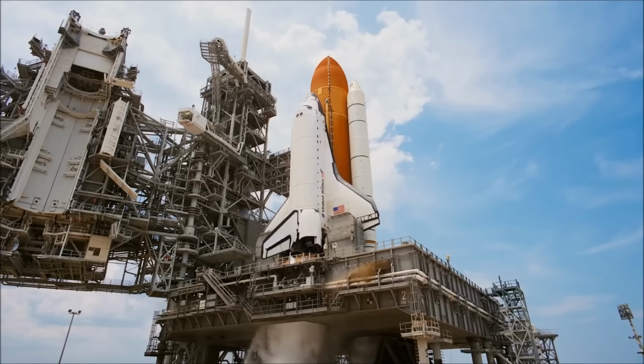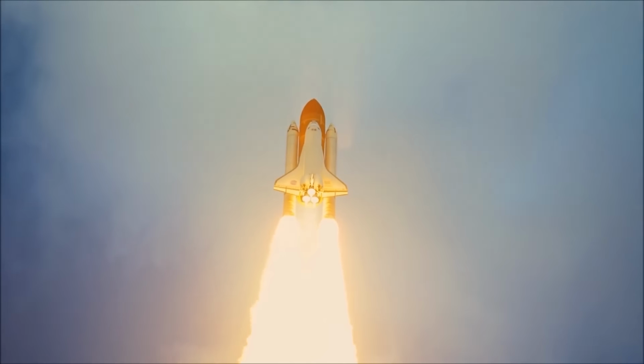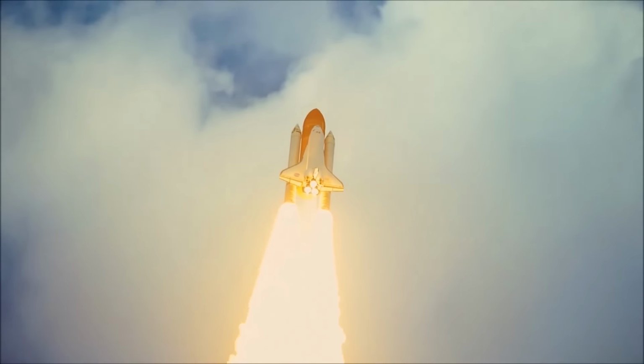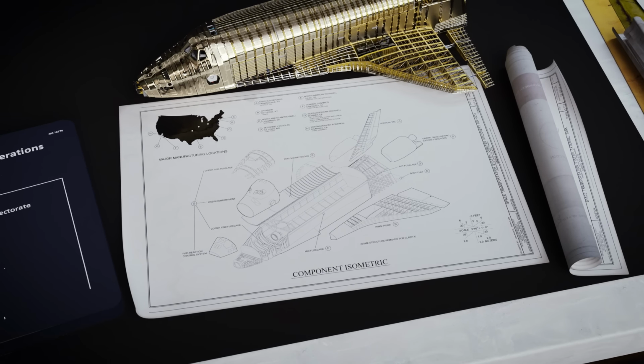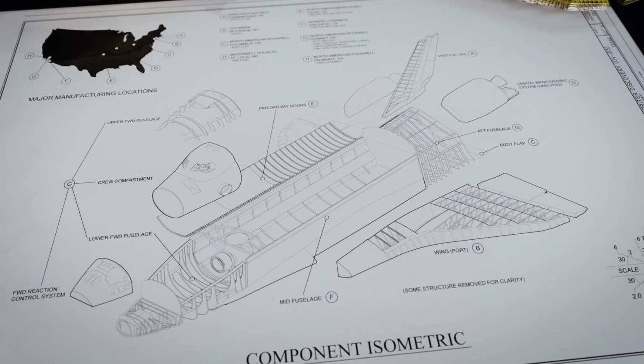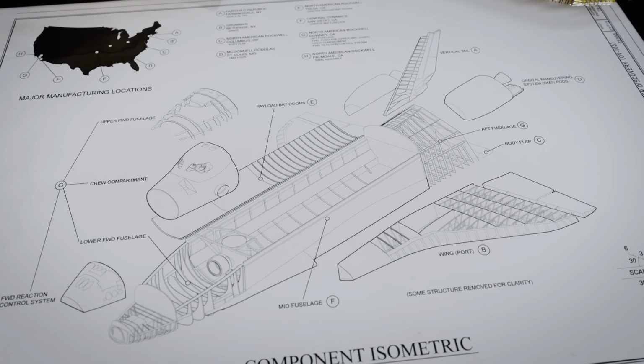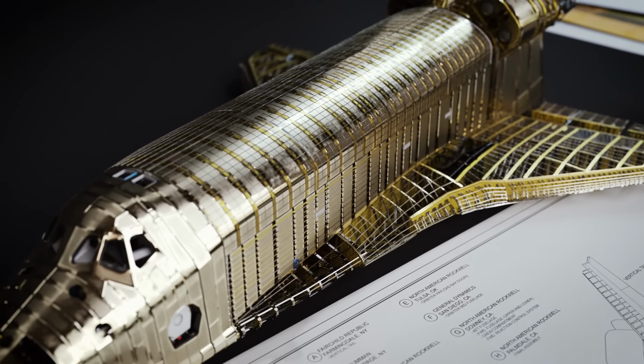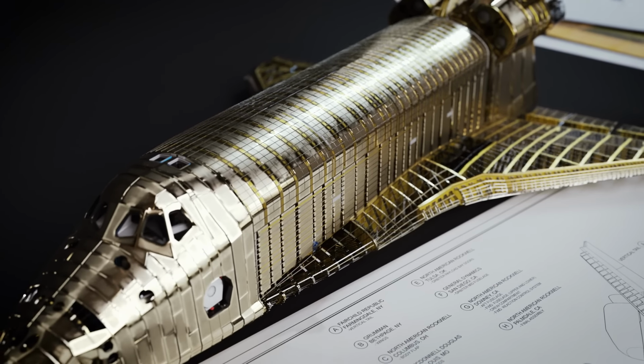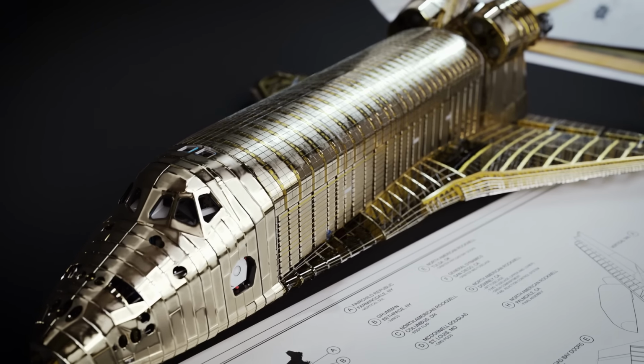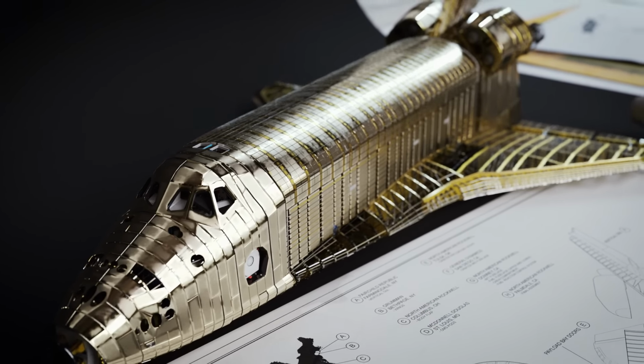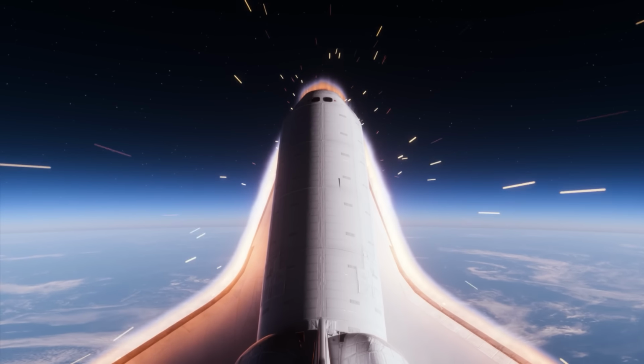Inconel X is too heavy, about 180% heavier than an equivalent aluminium airframe, a massive issue for an aircraft designed to be carried to orbit. The Space Shuttle's airframe, therefore, is not made from Inconel X. It is composed of lightweight aluminium, which has a max operating temperature of just 177 degrees, 5 times lower than Inconel X. The orbiter would experience temperatures 10 times greater than this for extended periods of its re-entry flight.